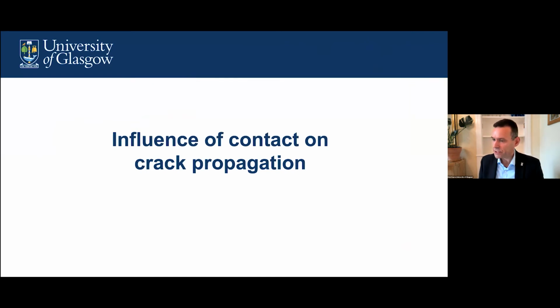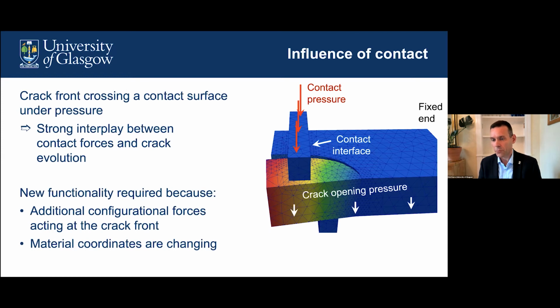Okay, so that's the influence of internal stresses, but we then came across another big problem, and that was where we have contact. So essentially, we've got a problem where we have two interacting parts, and the crack front crosses the contact surface that is under pressure. The challenge is where you have a crack that is passing across that interface, and you have a strong interplay between the contact forces and the crack evolution. And that required, again, some extension to our formulation to capture this complex scenario.